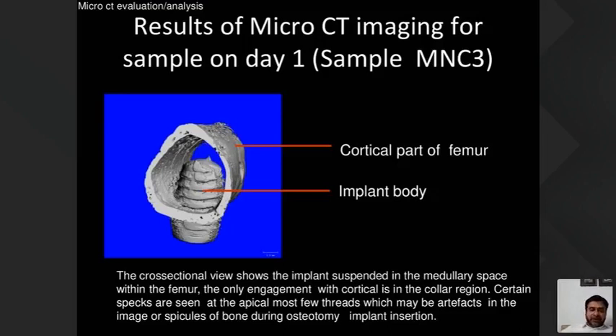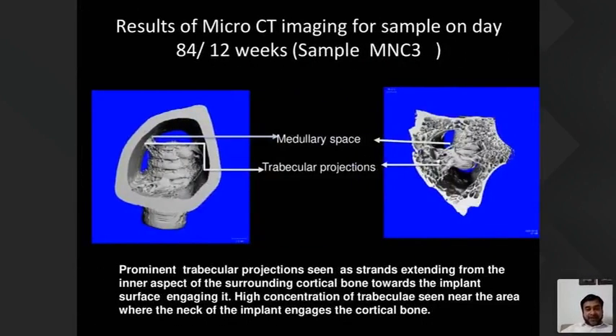So here is the CT image of the 12-week sample. Voila. You have a meshwork of trabeculae growing from the periphery to the implant from all over and engulfing the implant like a meshwork. You can see right here in the picture how it has engulfed the implant all around the endosteum of the femur. Now, this was very astonishing to us. We had got bone in areas where there is not supposed to be any bone in the first place. So there was something about the surface treatment and the microgeometry of the implant that led to non-contact osseointegration, or bone forming all around the implant, where it did not exist.